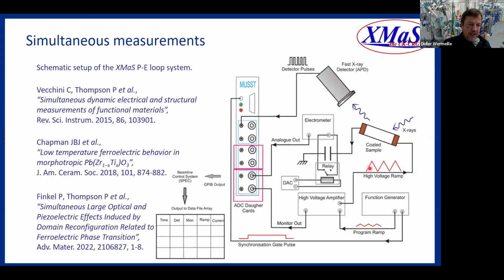One thing that has been developed also is simultaneous measurements for the standard setup here with an APD detector, but possible to apply voltage across the sample with a function generator, so we can generate different signals, and then an electrometer, and all this goes through the MUSST card, and we can record the different signals at the same time.